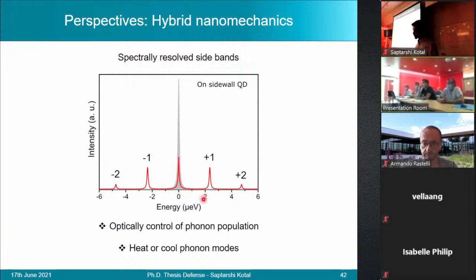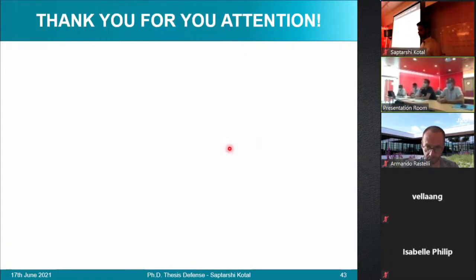The coupling between the emitter and the mode is sufficiently strong to be able to isolate even the transition corresponding to the 2-phonon state. Therefore, by optically selectively exciting one of these states with a spectrally thin laser, we could conceive of controlling the phonon population in the mode, thereby either heating it or cooling it. With that, I thank you for your attention.